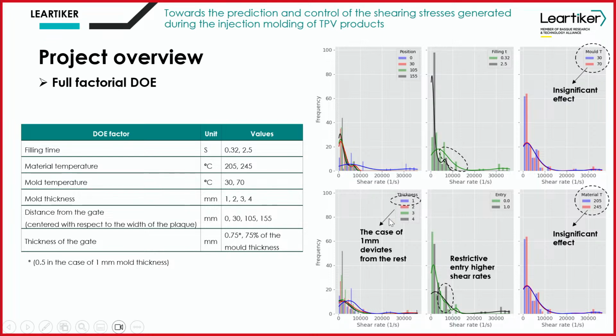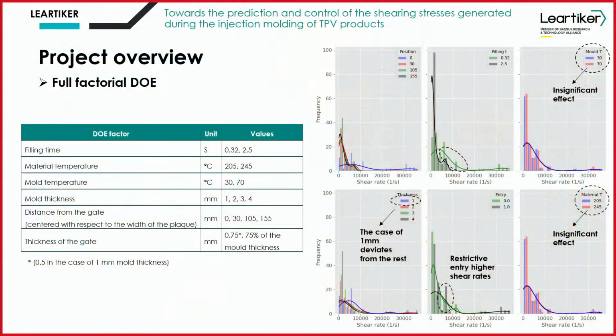And it was interesting also to observe, if we compare the graphs, the curves, that the 1 millimeter case deviates a bit from the rest. So in the case of 2, 3, and 4 millimeter, the shear rate effect is similar, but in the case of the 1 millimeter, the influence of the parameters on the shear rate deviates a bit from the rest. And in terms of the filling time, we can also observe that with a lower filling time, we achieve higher shear rates, okay?